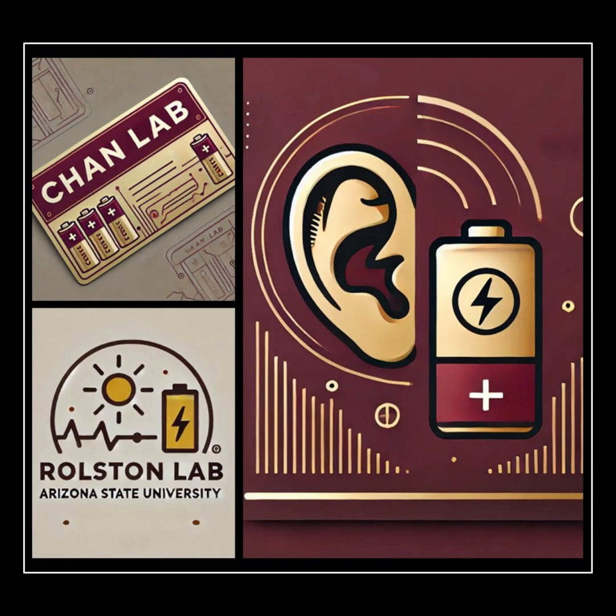For the listener, what does cutting that resistance by almost 50% actually mean in terms of using a device? It means ions move much more easily across that interface. So you'd expect significantly faster charging, the ability to deliver more power when needed, like accelerating an EV, and potentially a longer overall battery life because there's less resistance causing degradation. It makes the whole process much more efficient. That's a tangible benefit, and you said that was only treating one side.